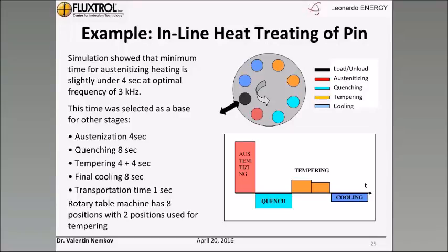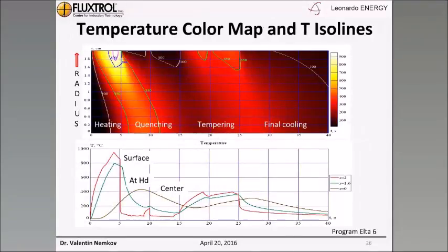For austenitization, 4 seconds, then 8 seconds, 2 stations for quenching, 2 stations for tempering, and then two or more stations for final cooling. The installation could be made as a linear or rotary table type. Here we have the results, very well presented: the distribution of temperature in the radius of the part during all the stages of processing. Here we have the heating, then we have 1 second transportation to quenching, the first stage of quenching, the transportation, the second, and so on.